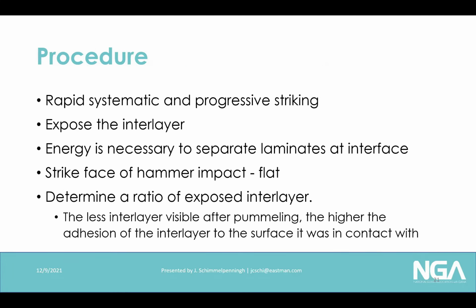So how do you do this test? It's very rapid, and I can go through all the words of it, but we do have a video that will show it to you. So I think that will be a little bit more illustrative, but it's a rapid, systematic, really hammering of the glass. It's progressive striking. And what you're trying to do is expose the interlayer. You're trying to get the glass that easily comes off of these products to come off so you can understand the level of adhesion you have. There's a certain amount of energy necessary to pound this glass off of it and separate the 2 surfaces, the glass and the interlayer. And the strike face of the hammer needs to be as flat as possible.